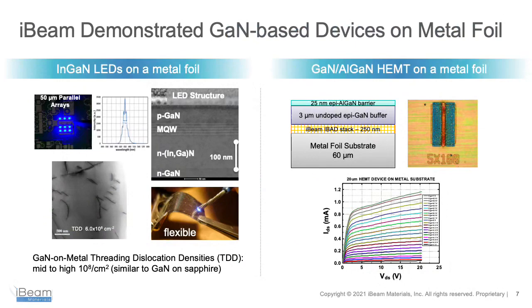Here we show the devices that we have made using epitaxial gallium nitride on metal, LEDs and transistor devices. Based on the threading dislocation densities that we observe in our gallium nitride material, which is similar to that of gallium nitride on sapphire, we believe that we can ultimately reach the performance of LEDs on sapphire, although we're not quite there yet, and we have to improve our light extraction efficiency. On the right side, you see our first in the world high electron mobility transistor, fabricated directly on metal foil. Ultimately, we would like to integrate the gallium nitride LEDs with the gallium nitride transistors.